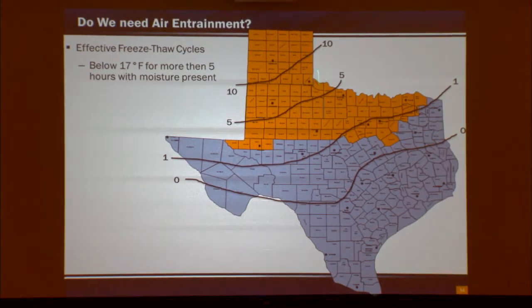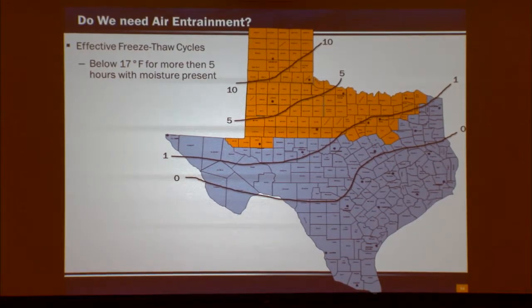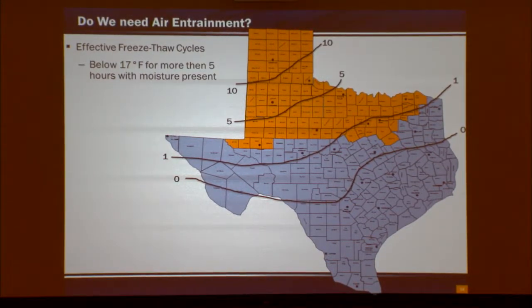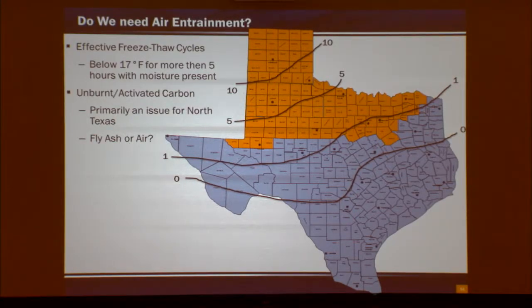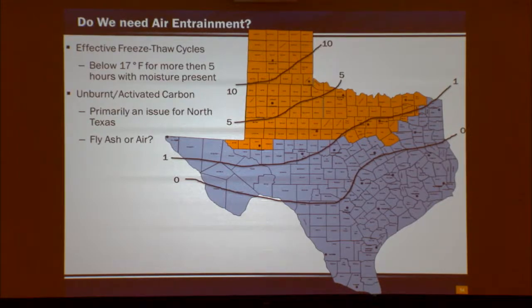Okay. But we don't have very many freeze-thaw cycles, and the important thing about freeze-thaw cycles is they need to be wet freeze-thaw cycles, right? We need to have moisture to drive the freeze-thaw deterioration. So we don't have very many, but we do have some. So the question becomes when you get into fly ash. I want fly ash in my concrete, but there's an issue that the unburnt carbon in the fly ash consumes the air entraining admixture. And therefore, you're moving along, you're going fine, then you get a bad load of fly ash, and it kills your air.